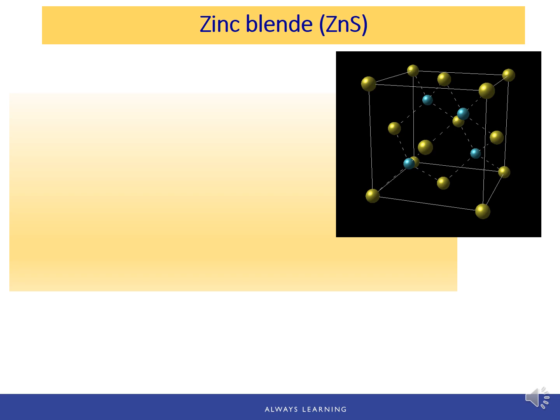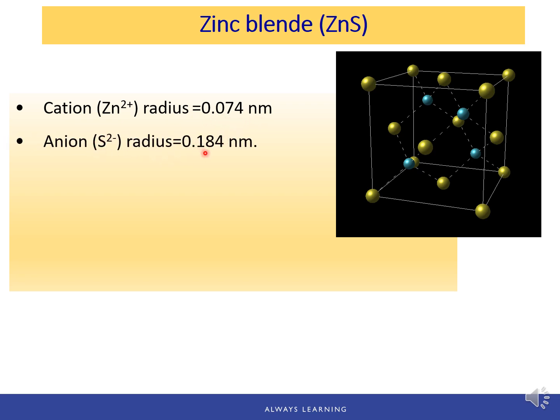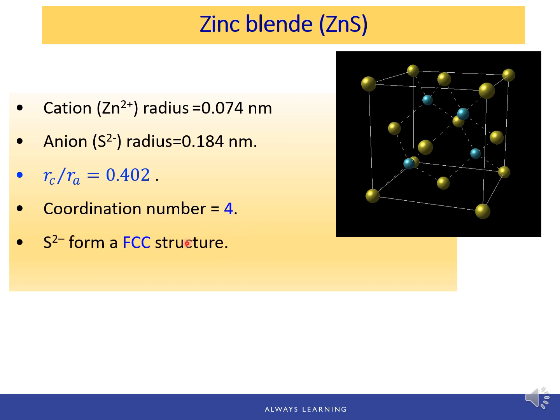A third AX structure is one in which the coordination number is 4, which is the zinc blende structure. The radius of the cation is 0.074 nanometer and the radius of the anion is 0.184 nanometer. We can then calculate the ratio of the cation over anion, which is 0.402. Checking the table for the critical radius ratio, the coordination number must be 4 to reach a stable structure. Therefore, the anions will form the FCC structure, with a certain number of cations fitting into the interstitial sites, which will be tetrahedral interstitial sites.